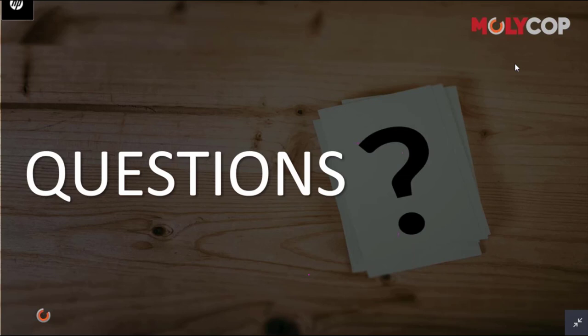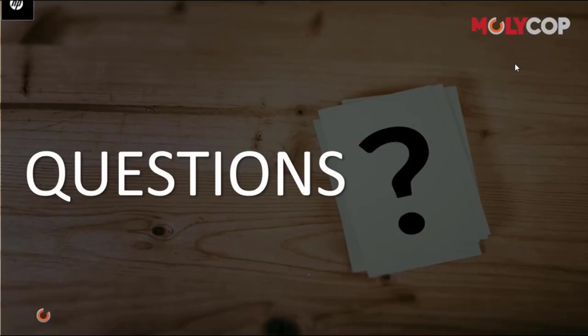But it depends also on the motion of the mill, because if you have very aggressive liners, your motion is cataracting. You are not going to promote the cascading. So you have to make a combination between the cascading effect and the grinding media size. Another thing is you can use smaller balls, but your feed size is very fine. It's less than 1 inch, or no higher than 2 inches.